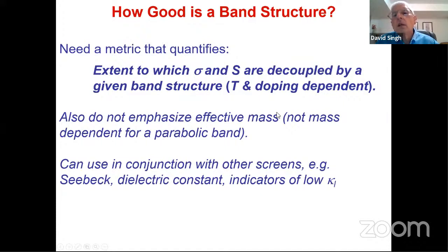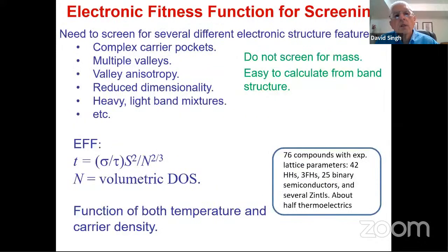So we wanted to find a screen that we could apply to band structure. And so what we came up with was a so-called fitness function. And this is the fitness function T. So we wanted something that you could easily calculate from the band structure with the codes that people have. And so you can easily calculate something called sigma divided by tau. This is the conductivity, but without the scattering time. So it's just a band structure quantity.